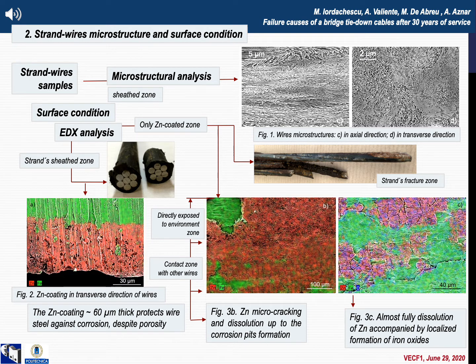Figure 3b shows the main differences in the zinc layer appearance on the wire surface, namely in the outer zone of the strand and in the contact with other wires. The first is of rough appearance due to both the galvanizing process and the oxidation and formation of porosities by zinc dissolutions up to the corrosion pits formation, while the second is smoother with transverse microcracks as a result of the combined action of the wire's contact, the applied tensile load, and the environment aggressivity.